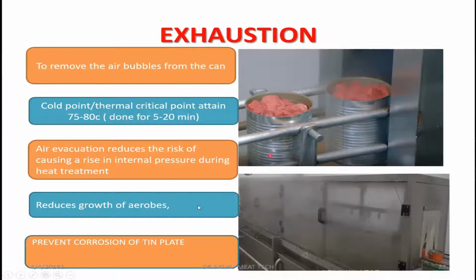So what is the advantage of exhausting? It reduces the microbial loads. Basically it removes the oxygen, so oxidation will not take place. If oxygen is present and the tin coating is not proper, there is a chance for corrosion to take place. To prevent that, we do the exhaustion process. Exhaustion removes the atmosphere inside the cans or inside the food materials. Here the can will be kept in the exhaustion chamber. Inside that, high pressure steam will be injected and the temperature will be maintained around 75 to 80 degrees, and we can go up to 85 degrees.